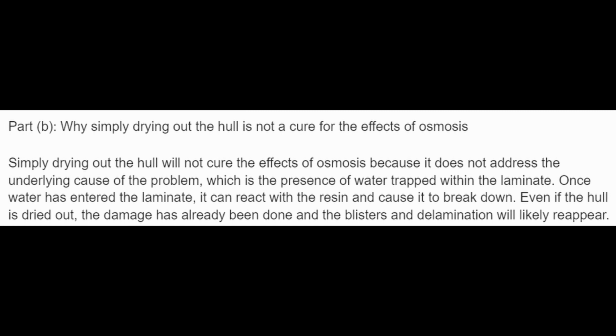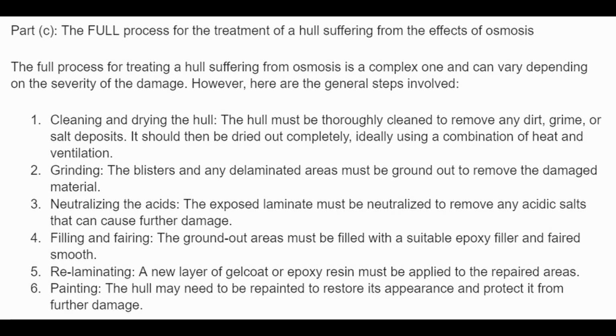B. Why simply drying out the hull is not a cure for the effects of osmosis. Simply drying out the hull will not cure the effects of osmosis because it does not address the underlying cause of the problem, which is the presence of water trapped within the laminate. Once water has entered the laminate, it can react with the resin and cause it to break down. Even if the hull is dried out, the damage has already been done, and the blisters and delamination will likely reappear. C. Full process for the treatment of a hull